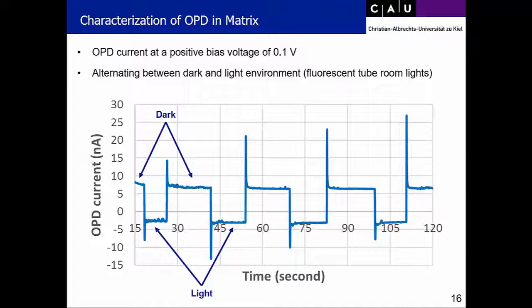We characterize these at a positive bias voltage of 0.1 volts. And we basically just did an experiment where we start with a dark environment, and we see an OPD current in the nanoamp range of about 8 nanoamps. And then we turn on the light in the room. So this is just the fluorescent tube room lights. And you can see the switching behavior here. So then the lights are turned off again, the lights are turned on again. What you also see here for these devices is that we get quite these spikes, and they even build up more, so there are definitely also capacitive effects going on in this matrix, which is also something we need to investigate. But we could show with these experiments here that we have successfully also fabricated the OPDs in the matrix.